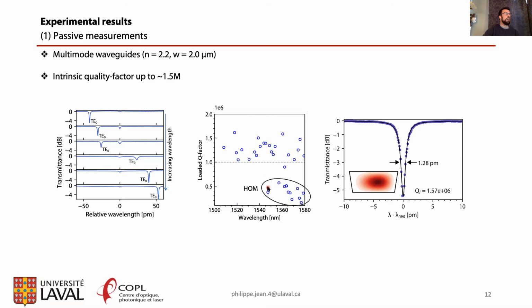Here we also observe higher order modes that had much lower quality factor. And the waveguide was actually very multimode because the index is relatively high at 2.2 and the width of 2 micron means that the waveguide actually supports multiple modes. And this was observed as well in the spectrum. If we look at the transmittance of multiple successive resonances here, we see the avoided mode crossing phenomenon, where two resonances will kind of march over one another, but never really cross.